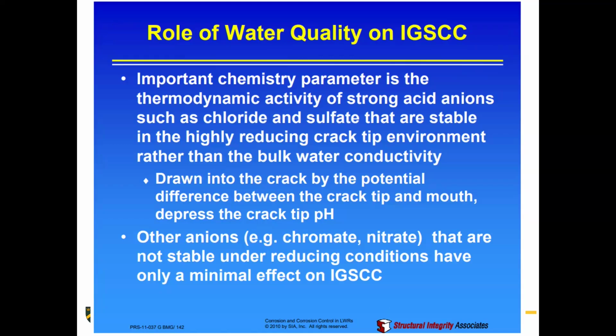All right, so let's go on to the role of water quality and the effects of these contaminants, or impurities rather, and what role they can have. So an important chemistry parameter for thermodynamic activity: strong acid anions, such as chloride and sulfate, are stable at highly reducing crack tip environment rather than the bulk water conductivity. So the grammar's kind of odd here, I apologize. Basically what's happening in this case is these strong acid anions, chloride and sulfate, are going to be more stable within the actual crack tip itself. You can imagine how this could be very bad news for continuation of that crack tip. So water chemistry is an absolute must in terms of purification. When it comes to these things, you do not want chloride in your reactor, period.